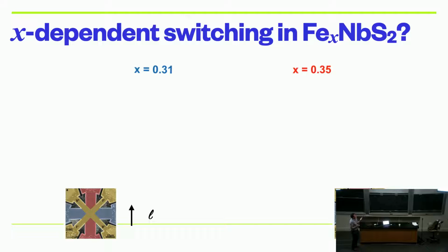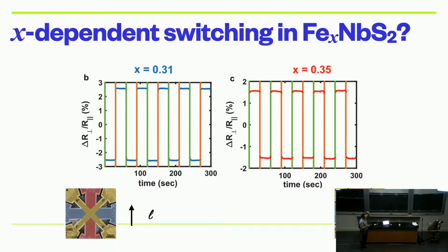But anyway, there was something pretty weird about all this. You could change the intercalation just a little bit from 0.31 to 0.35. So it was about 1/3, but you could actually change the intercalation a bit. And here's something interesting that happened. Can anyone see the subtle difference? These are the pulse trains again, the north-south direction, the east-west direction, low resistance, high resistance, low resistance, high resistance. Can anyone notice the difference between these two things?